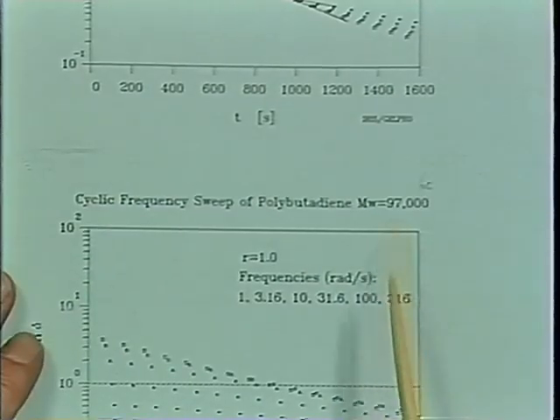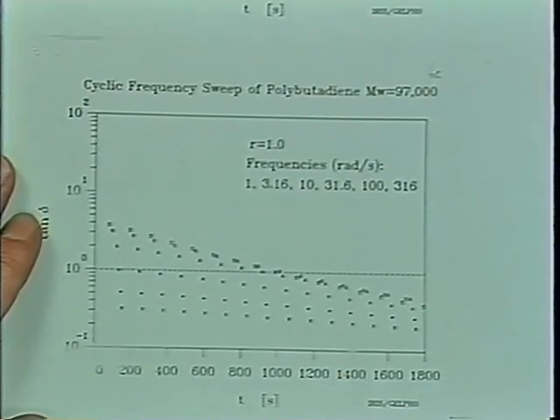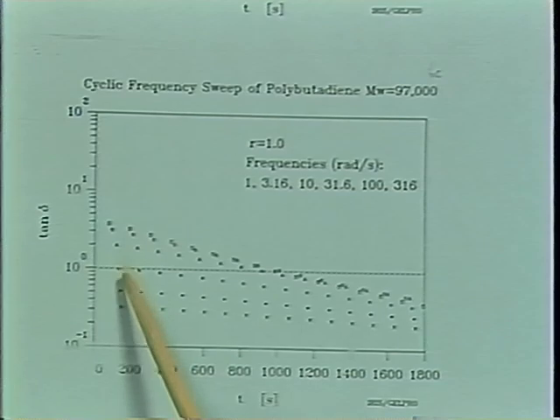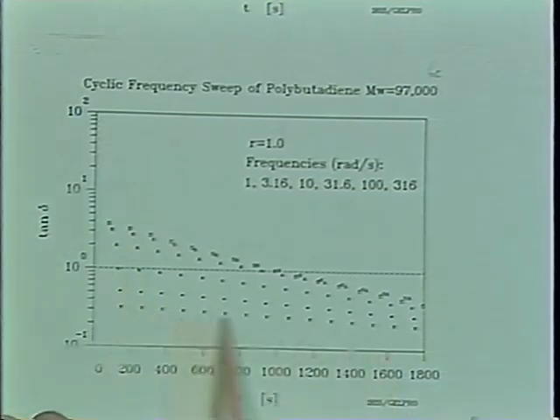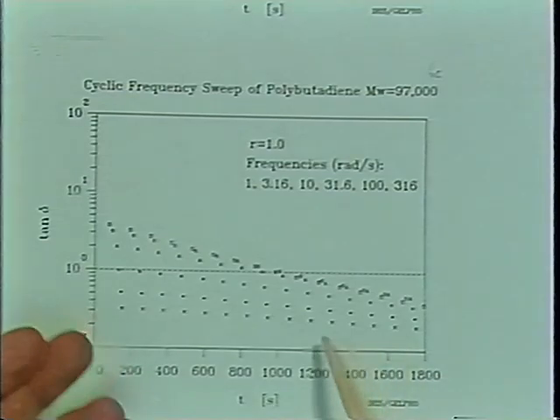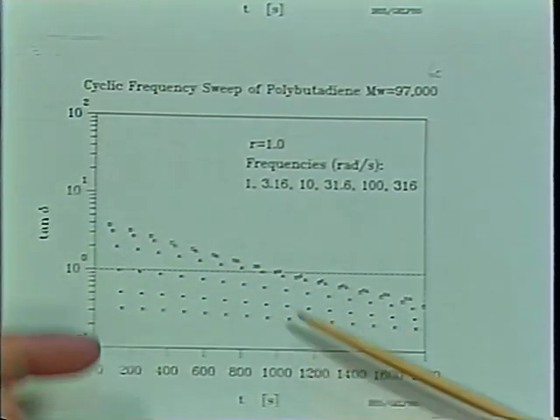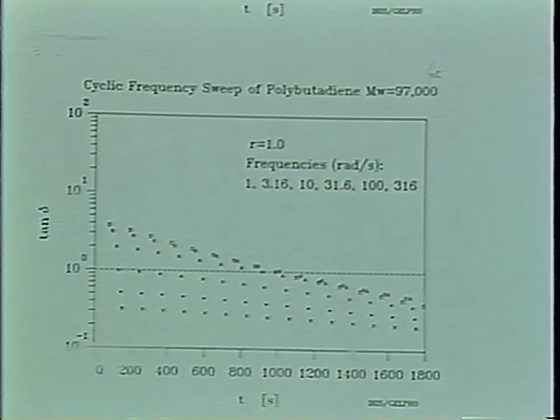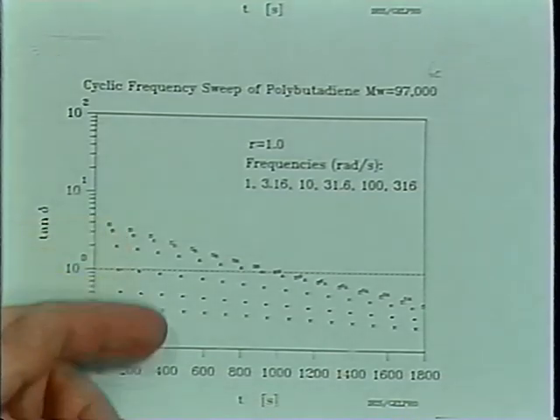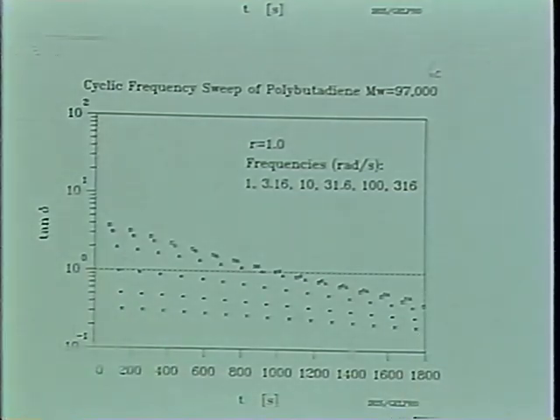However, if we go to the 97,000 molecular weight, you can see tan delta within our frequency range. These are different data taken at different frequencies as a function of time, and they never cross. So people might just look at this fingerprint here and say, oh, you wouldn't see self-similar behavior at the gel point. Look at this here, it never occurs. It does occur, but outside the experimental range. It's very, very difficult to decide on new experiments which would tell us the gel point of those highly entangled materials.